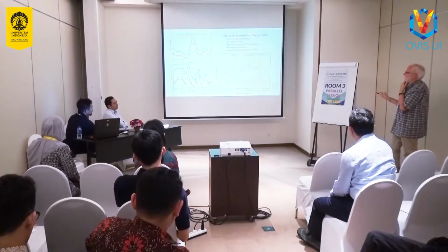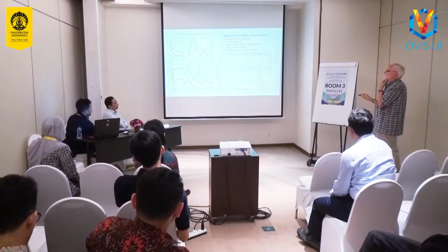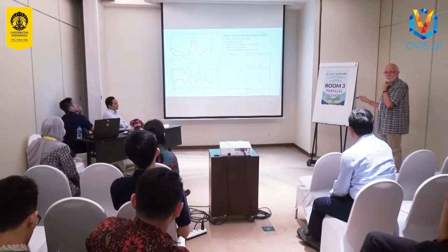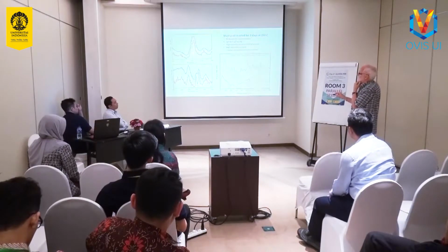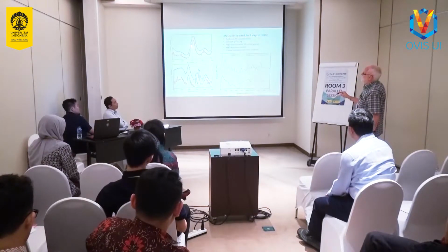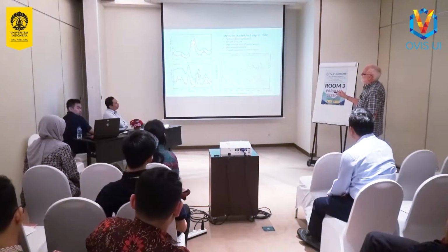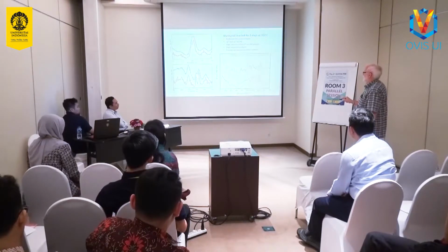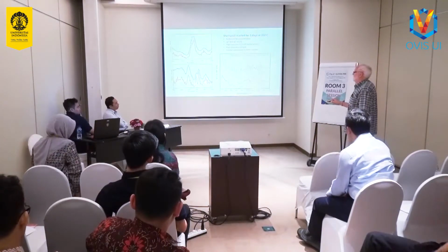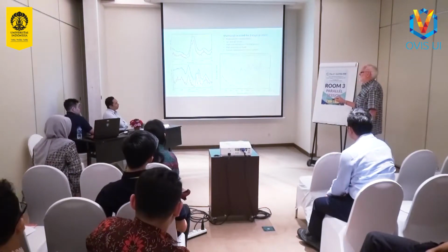This catalyst is still active. It's still converting methanol to gasoline. It's lost some of its acid sites, but it still has a number left. We can see that. These are CH stretching vibrations, and we can distinguish between aliphatic CH3 groups, CH groups below 3,000 wave numbers, and aromatic CH groups above 3,000 wave numbers, and they're resolved in this instrument and in this one. And then in the low frequency region, we see vibrations again typical of methyl groups and of aromatic species.